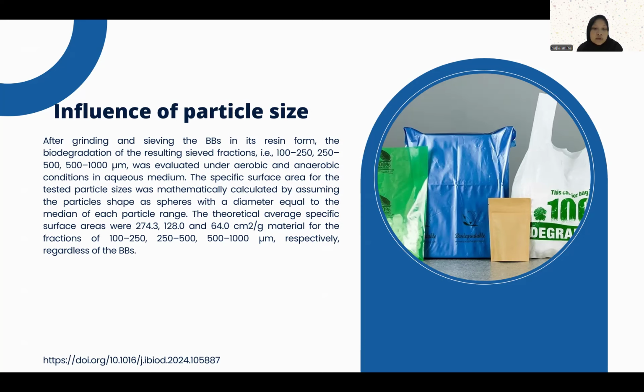Three theoretical average specific surface areas were obtained: 274.3, then 128.0, and then 64.0 square centimeters per gram of material for the fractions of 100 until 250, 250 until 500, and 500 until 1000 micrometers respectively, for the BBs biodegradation bioplastics.